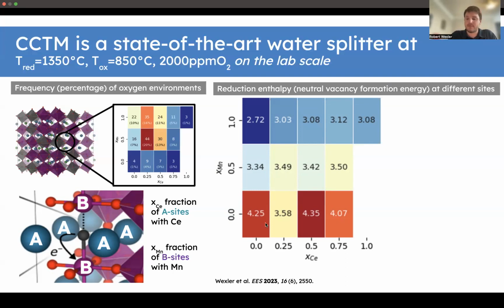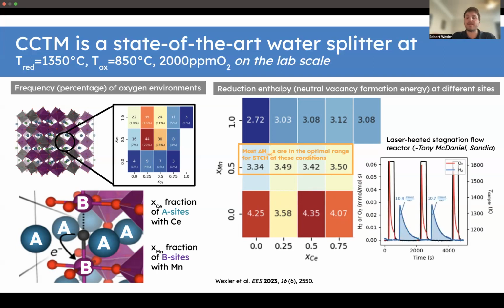And if we narrow in on the range that's optimal for STCH, clearly we can see that the most frequently observed vacancies, with the exception of maybe these two right here at the top at X_Mn equal 1, are all right in that window for STCH, the optimal window. So we have quite a large fraction of the vacancies that could form in the crystal having the right reduction enthalpy. And this bears out in experiments.